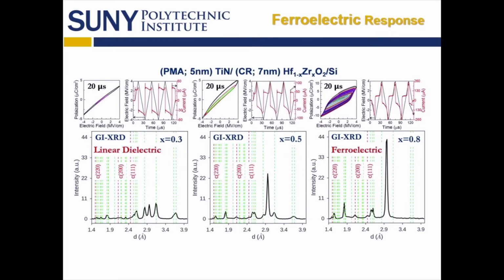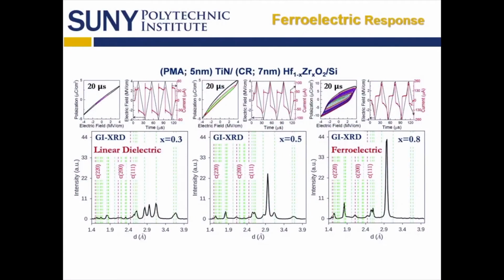And the diffraction patterns here are grazing incidence X-ray diffraction patterns taken at a synchrotron, and above is the electrical data, and in particular for the charge or polarization. So polarization talks about built-in charge, but the charge versus electric field. You see hysteresis, especially in the 20 microseconds data right up there on your upper right. And you see that as you cycle it a number of times, that hysteresis pattern changes. And there is some match between the X-ray diffraction data and that electrical data. Okay, but that is a full-blown electrical test structure.